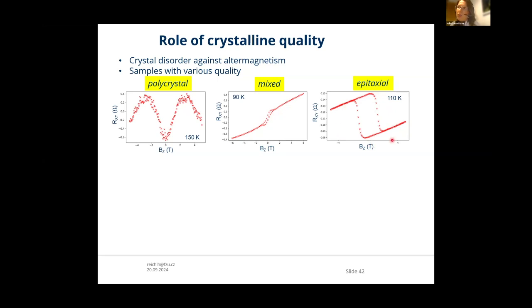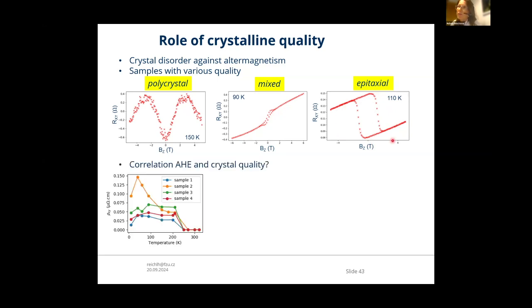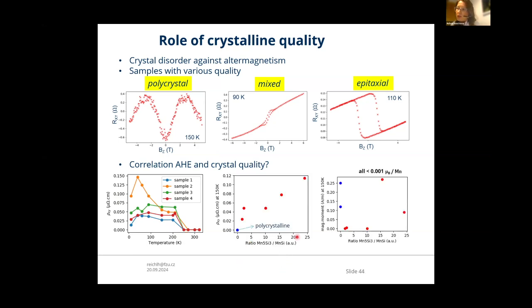This is indeed the raw data as it comes out of the measurement system. And we also asked, can we correlate it somehow with the crystal quality? We had a set of measured samples. All of them show some form of the anomalous Hall effect, and all of them have approximately a similar critical temperature. We also tried to compare the quality by looking at the XRD data, comparing the content of the ordered Mn5Si3 with some impurities which are unfortunately sometimes present there. By this ratio of the crystal phase of the Mn5Si3 and the impurities, which are the manganese silicon,